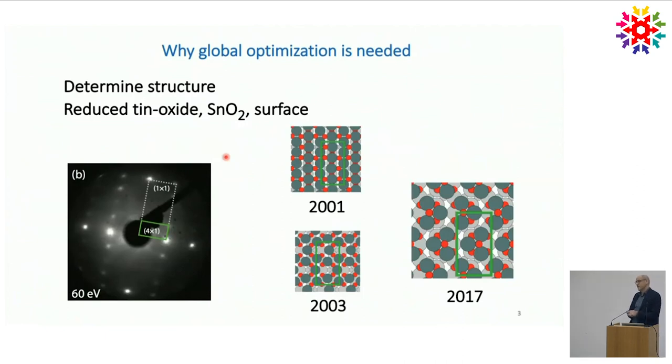Once you have seen it, you see that it seems a natural structure. If you look at it, it has a small cluster of tin, three oxygen, I don't know, three or five, and that is repeated along this direction and inverted, which is exactly what can also be revealed from the LEED pattern, that there is a glide plane on the surface. And you see why we have that glide plane: because then we can pack those clusters very closely. But getting the idea that this is the solution is not